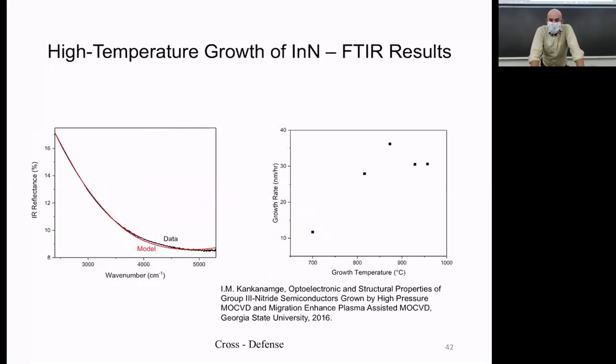Moving on, we can model the thickness of these layers using the FTIR data, using the work done by a previous colleague of mine who graduated from Georgia State as well. And we can find that as the temperature increases, we actually are getting an increasing growth rate at a certain point, and then it kind of stabilizes or plateaus. We probably needed to get more data there to figure out what was actually happening at this point. But the fact that the growth rate increases as temperature increases is a very exciting result. That means that we are not just seeing some fluke of one experiment, but as the temperature increases, there is actually an increased growth rate of indium nitride. So there is some promise in this technique.